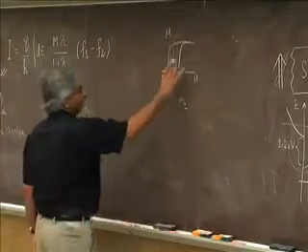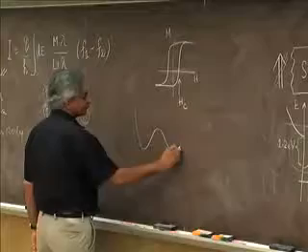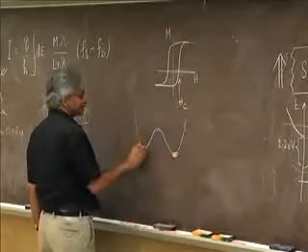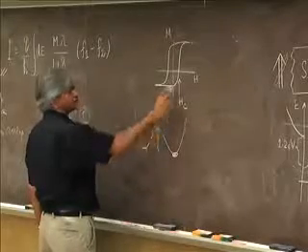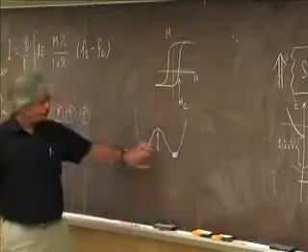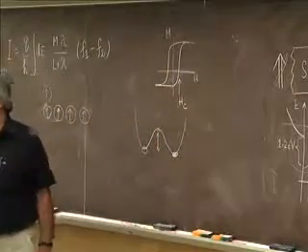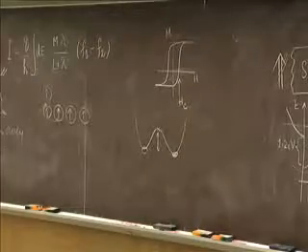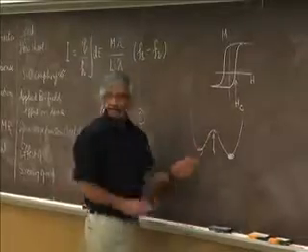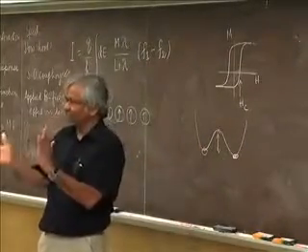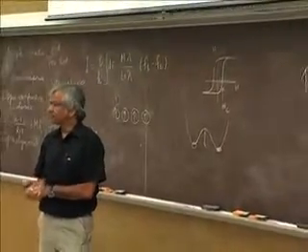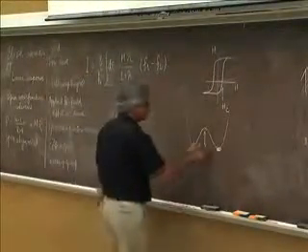And the way you think about this is as if there's an energy barrier. When you're here, it's like this. When you're here, it's like this. And this barrier is actually the product of HC and M saturation. That barrier determines the stability of this thing. And actually the barrier depends on volume. So in that sense, it is true that as you cut something down, the barrier goes down. But as long as the barrier is, say, about 1 electron volt,